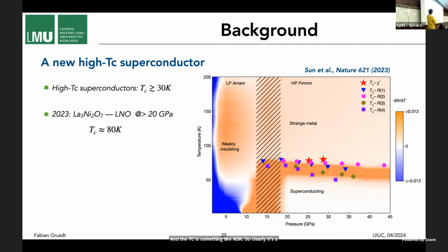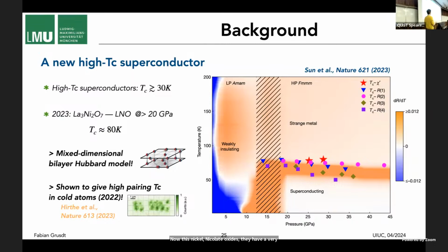Now these nickelate oxides, they have a very similar structure to copper oxides, and people basically immediately proposed that the type of physics you should see is basically a bilayer Hubbard model. So in the simplest terms, think of just a bilayer copper oxide type of lattice, okay, with nickel replacing the copper. But the point is, these systems, and I'll explain why in a second, are mixed dimensional in the sense that we don't expect there to be much tunneling between the two layers. But we do expect there to be super exchange. Okay, so it's exactly the type of trick that we played before in the cold atoms to get the stripes. That's the type of physics that seems to be at play here.